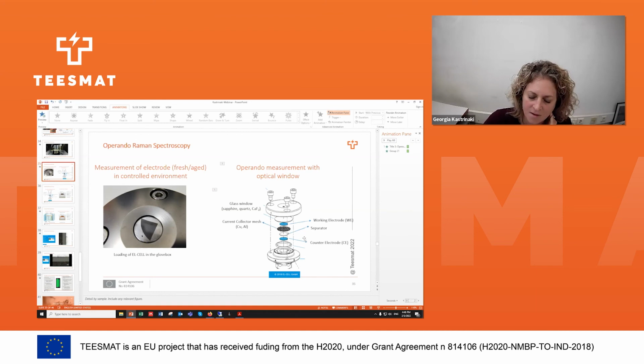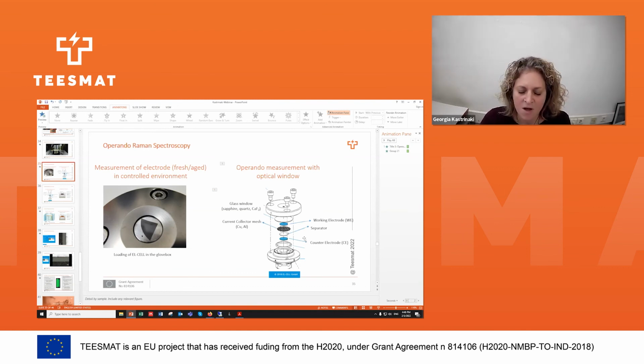Yes. Don't you have any trouble with the swelling of the active material with the beam focus? Yes, it is one of our issues. Actually, during high beam activity, because we are trying to optimize the technique right now, the electrolyte gets heated by the beam and increases its temperature. But what we have seen is that by using a longer laser wavelength, we have 532 but now we're trying 785, the increase of the temperature is much lower. This is one of the things we have tried to optimize the technique.